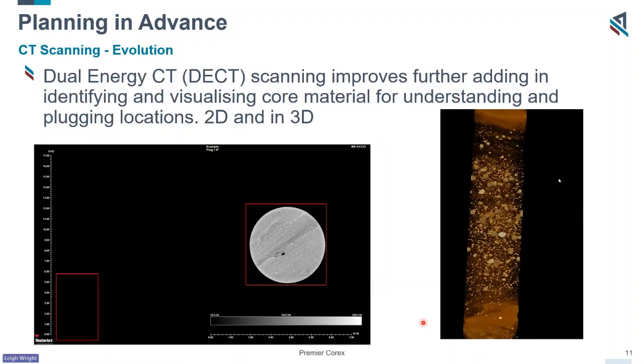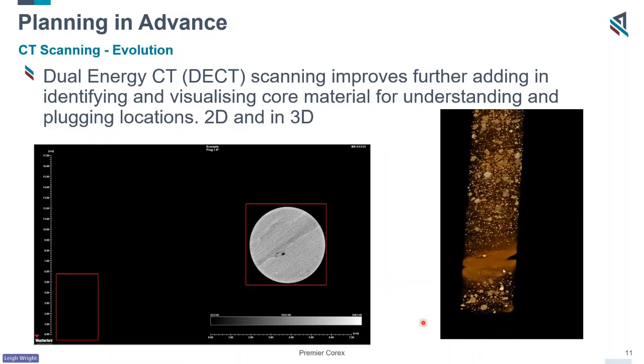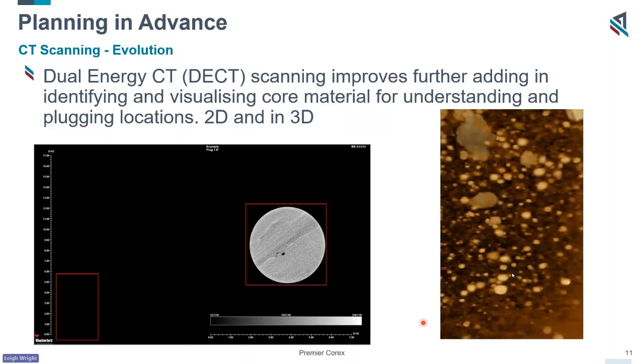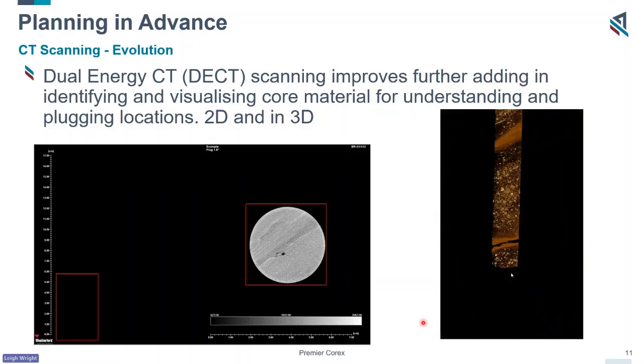So going back to the previous slides where you see the saltire effect across the core, you can see that the leaps and bounds that technology has come along is great. And with this leaps and bounds of technology, it improves the data that you get out because you're getting a higher confidence that you're plugging correctly, you're getting the right orientation of core, you're plugging through areas where you know that you're going to get a homogeneous sample, or even when it's a heterogeneous section, you're getting samples that you're plugging in areas that you know are going to give comparable plugs.